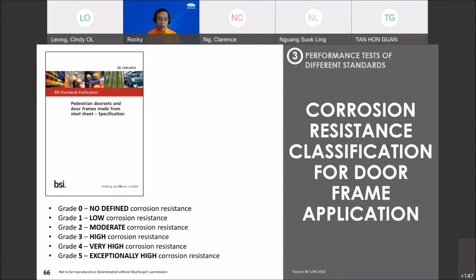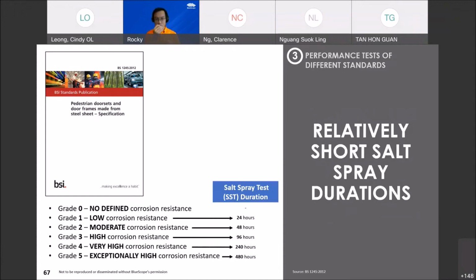What is the corrosion resistance classification? Over here you can see grade 5, the term is called exceptionally high corrosion resistance, and this is actually a direct quote from the standard itself. Exceptionally high corrosion resistance. And if you use this term and then you look at the salt spray test, the salt spray hour is only 480 hours. Exceptionally high corrosion resistance, right?